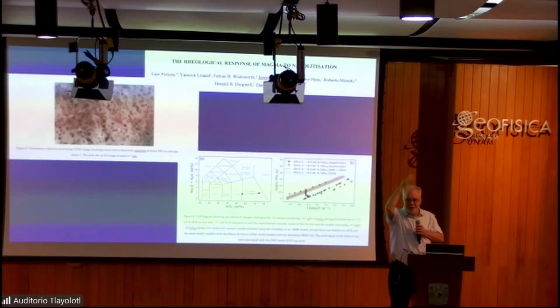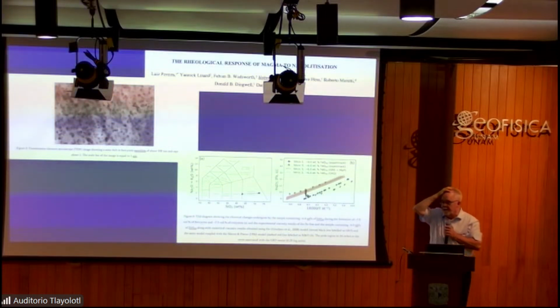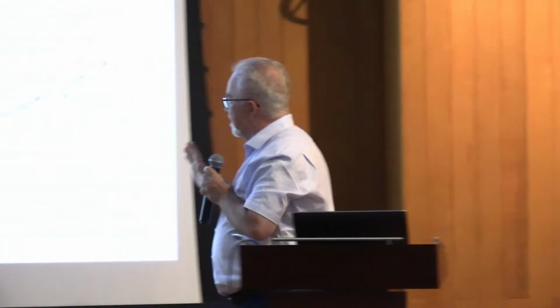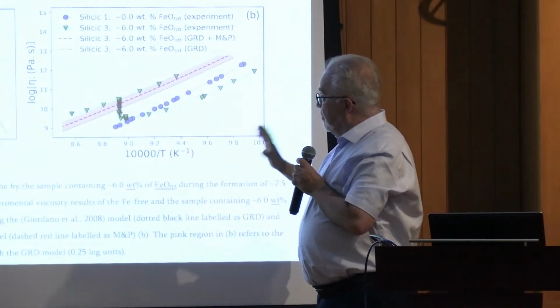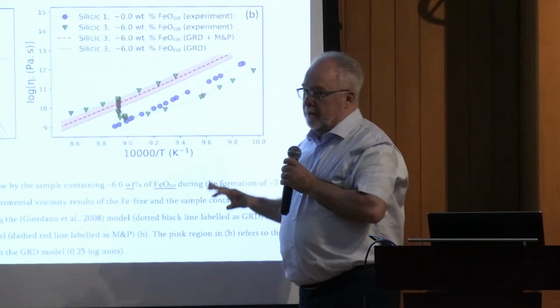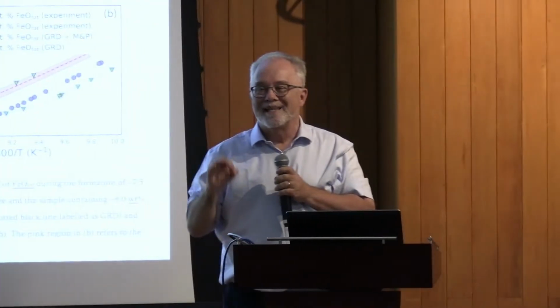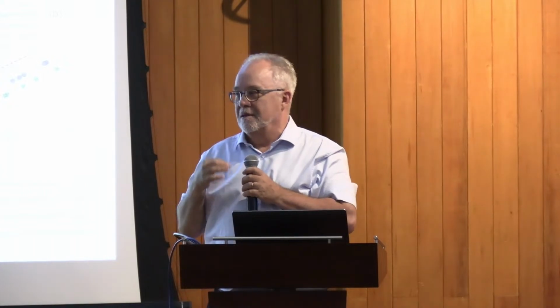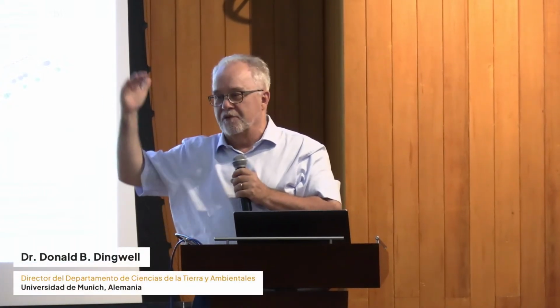So the first thing a physicist will do is put up their hand and say, great, you've discovered the suspension effect of physical obstacles, inviscid particles inside of a multi-phase material. But we say, be careful, because it's still a relatively small fraction by melt. And what we've discovered by doing this kind of work is that it is a chemical effect of the crystallization of the iron-bearing nanolites, which is pushing the viscosity.